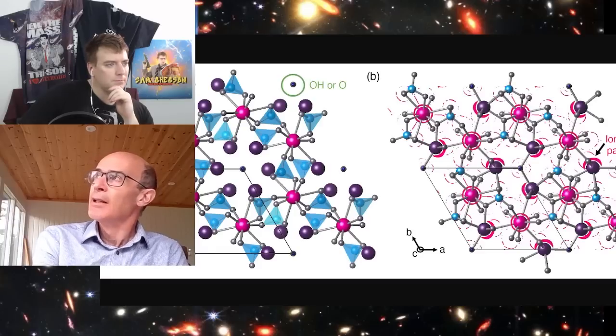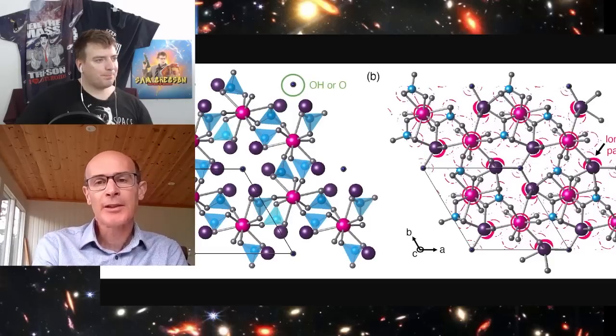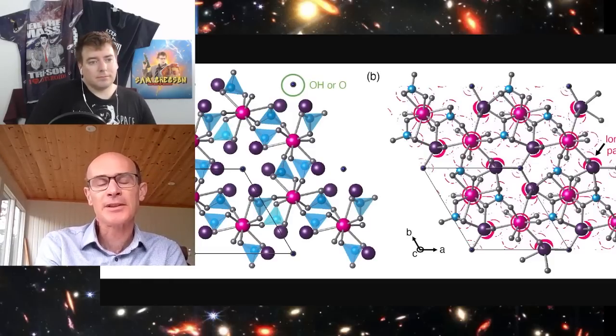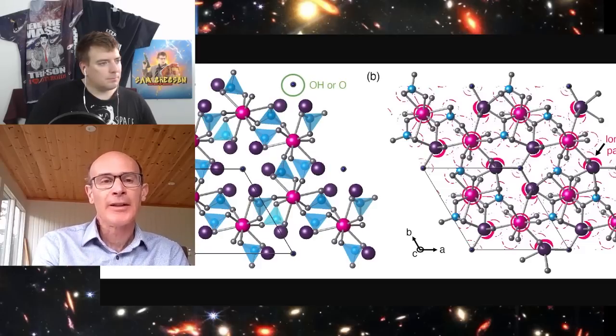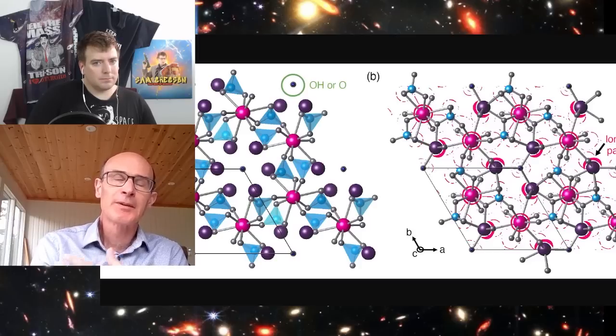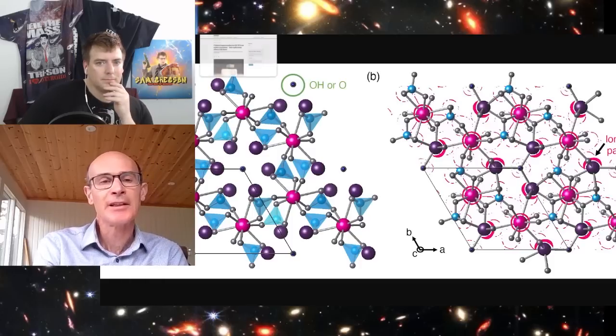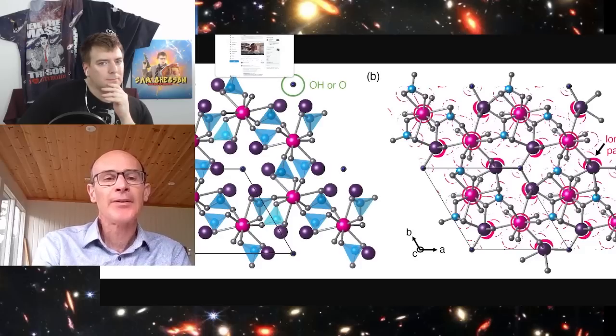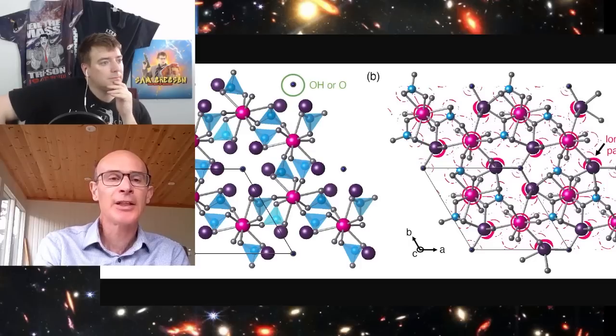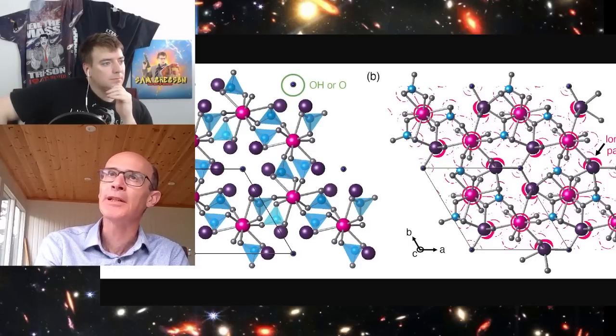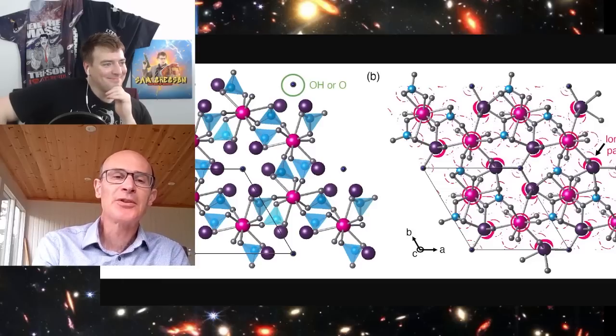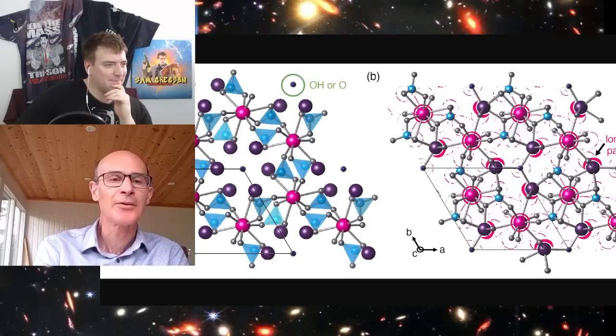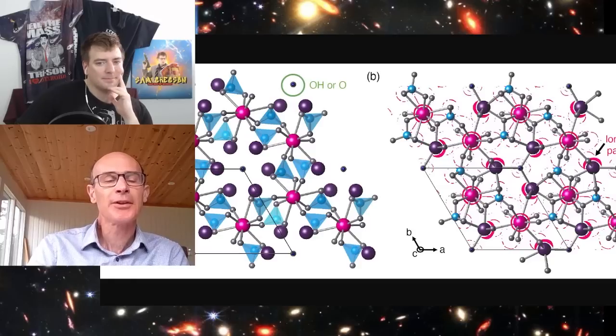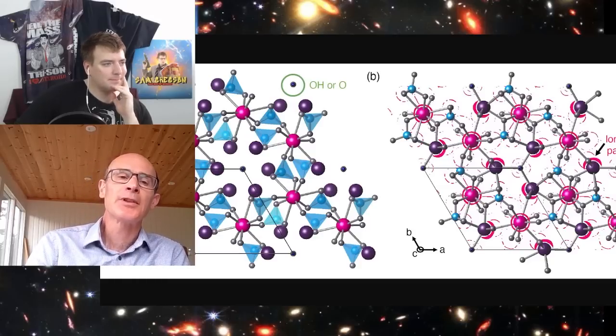Now, it's true to say that the history of superconductors shows that they sometimes appear when you're least expecting them. The copper oxide superconductors, which were discovered in 1986, were discovered when a magnetic insulating compound had its composition changed to slightly change the electron count in the material, and that turned the compound into a metal. And at low temperatures, it was discovered to be superconducting. So a general rule for discovering superconductors might be to introduce some mixed valence of any transition metal ions that you've got, move away from a simple stoichiometry, and then sometimes unusual effects appear.